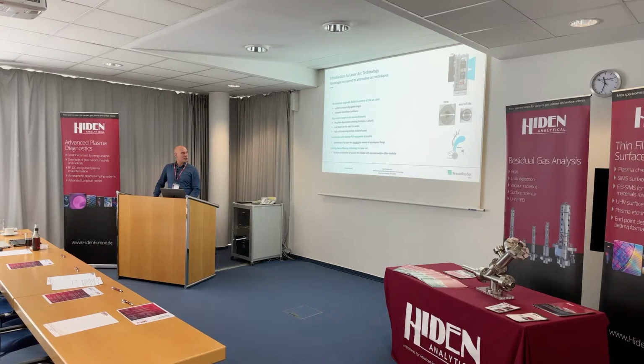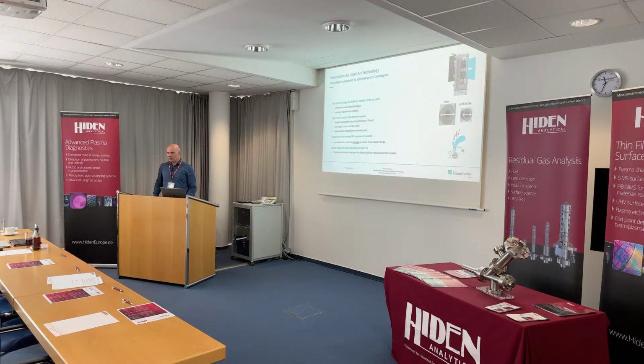These high volume targets also lead to longer coating processes and very thick coatings. We can do 20-30 micrometer thick hard coatings for several applications where it's needed. And of course, you can also do thinner ones. Then the targets you need are only about one per week or so, depending on how much you use your coater and how thick the films are. Okay, the combination with other PVD equipment is possible without a problem, but mostly people come to us and ask for a designated batch coater, and then we work with partners together to make this work for them.